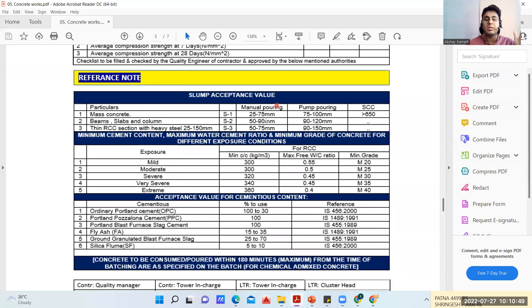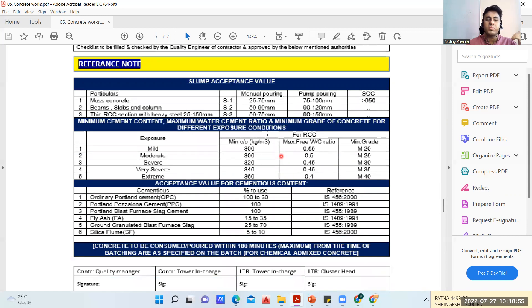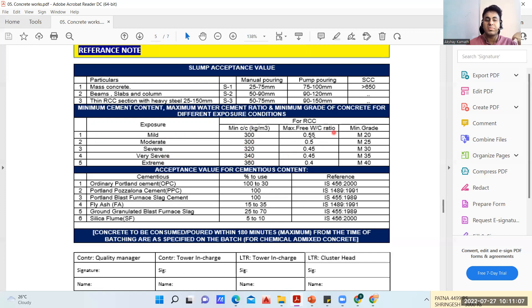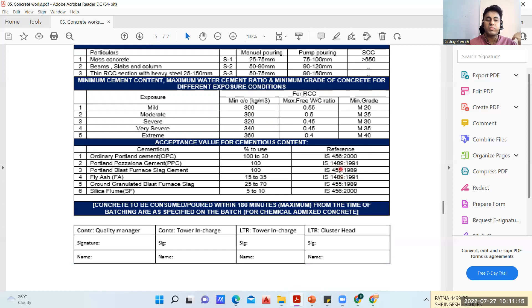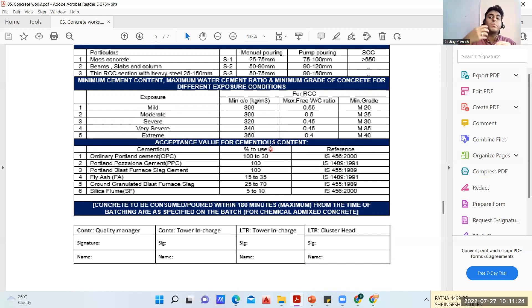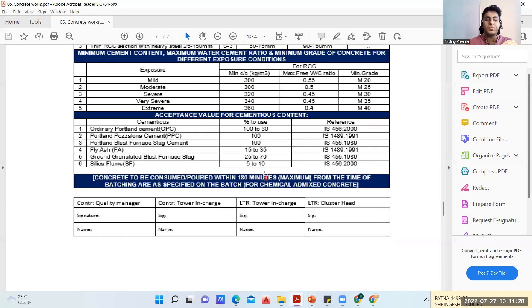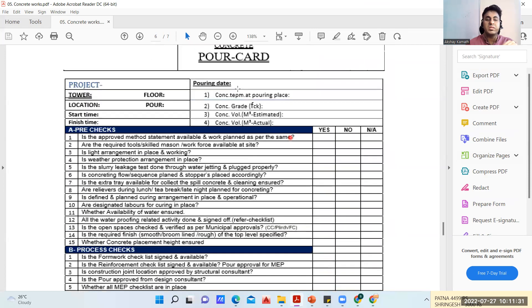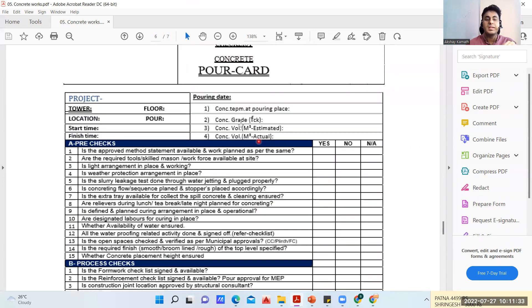This is a slump acceptance value which I had already explained, and this is how we decide the grade of concrete based on the exposure condition. How much is the minimum cement - if you're putting a mild exposure it has to be 300 minimum, if it is very severe exposure 340 is the minimum cement. This is the maximum water cement ratio you can keep. If you're putting your structure in very severe condition, you have to use minimum M35 grade of concrete. These are the references according to the code book. This is for cementitious content - if instead of only cement you're using silica, fly ash, GGBS and all, in what proportion or percentage you're supposed to use it is mentioned here.